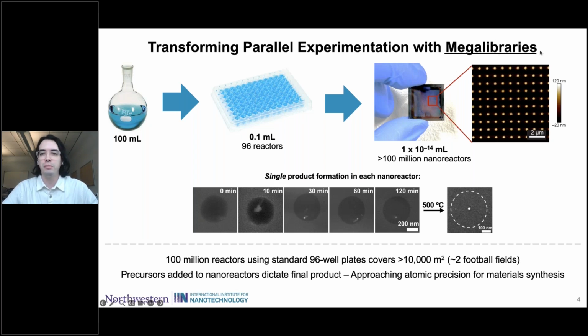And that's what this Megalibrary is, where we have these chips, which are just 2 by 2 centimeter chips that you can hold in your hand. If you zoom in, you have these reactors or wells, where each of these droplets is a volume of 10^-14 milliliters. So really shrinking it down from the 0.1 milliliter scale. Because of this small volume, we can now put over 100 million of them in this centimeter size chip. And so we now have this method of making these huge arrays.